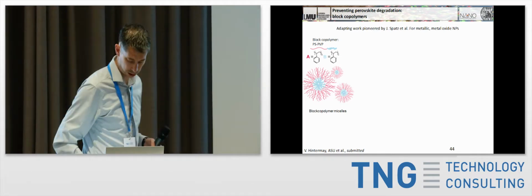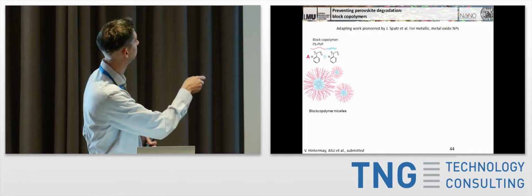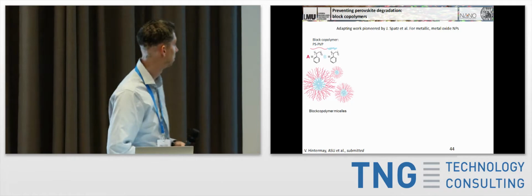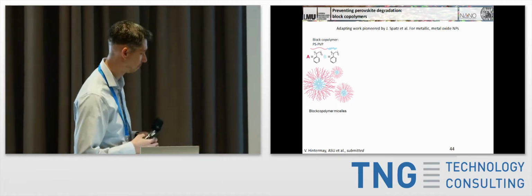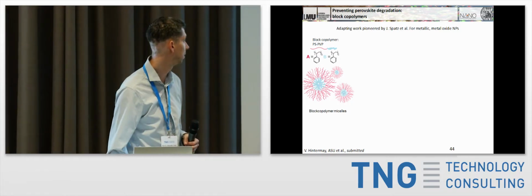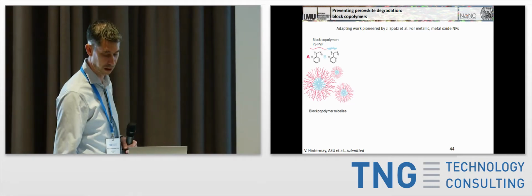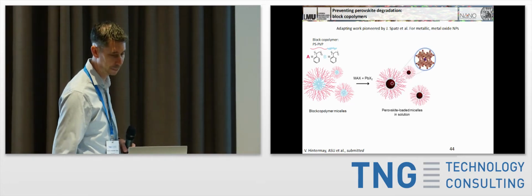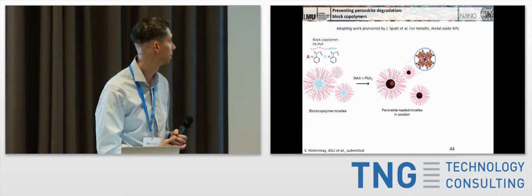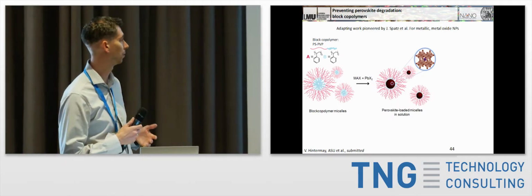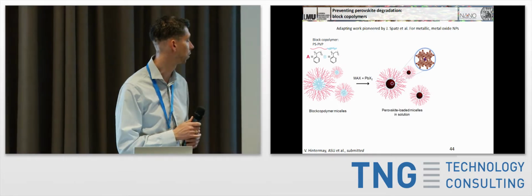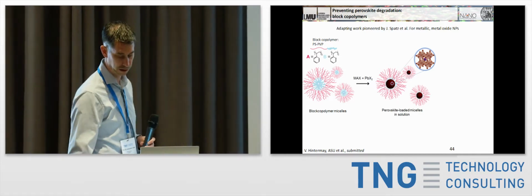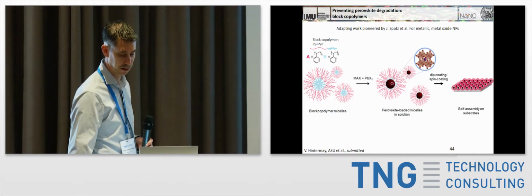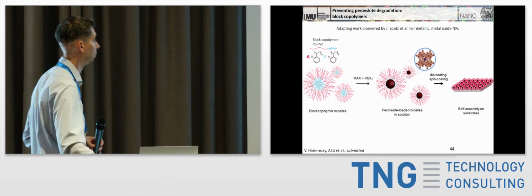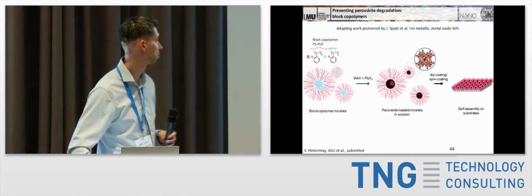So these are polymers that consist of 2 different parts and thus have a different effect in the surrounding medium, and so form these micelles. And what we get to happen is then we add the perovskite precursors to the solution. They don't like to be out in the solvent, but like to diffuse into the cores of these micelles, where they then form perovskite nanocrystals. And we can then take them together, form really, really nice monolayers on substrates, and start to look at their actual properties.